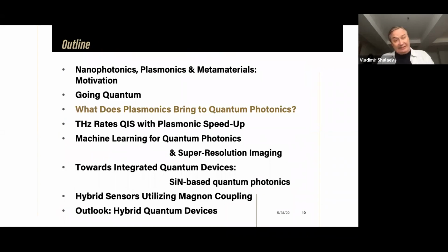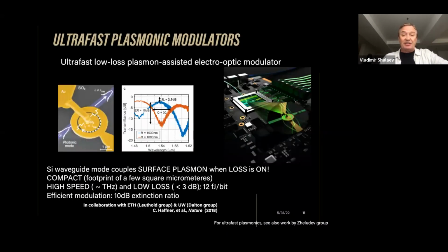So let me remind you what plasmonics is unique about and what it could do for quantum photonics. Let me start with this experiment we did some time ago in collaboration with ETH, with a group led by Jörg Leuthold. It just shows that you could have these ultra-fast plasmonic modulators. The idea is very straightforward. Let's say you have this gold ring resonator, as is shown here, and in the gap, you fill it with an electro-optical organic material, which changes its refractive index when you apply voltage.